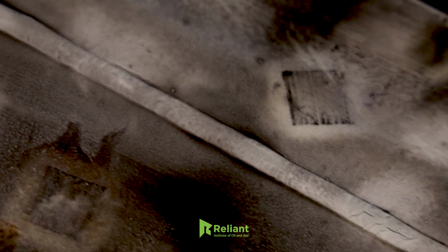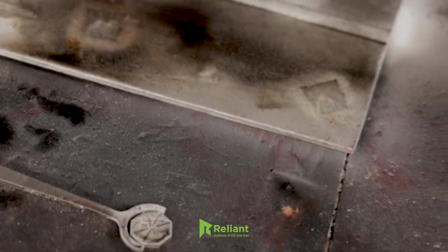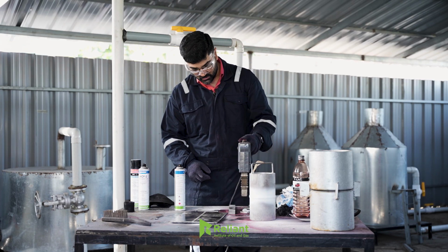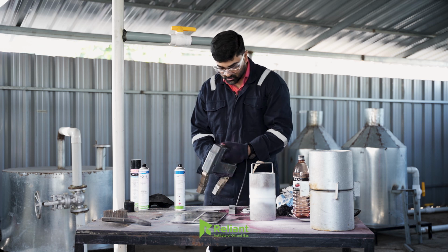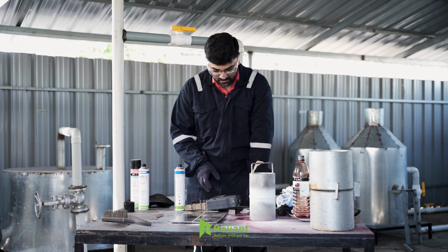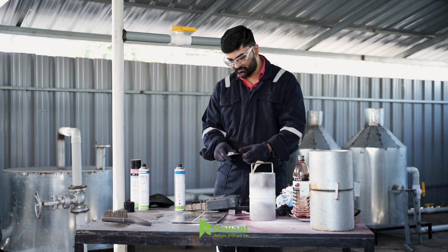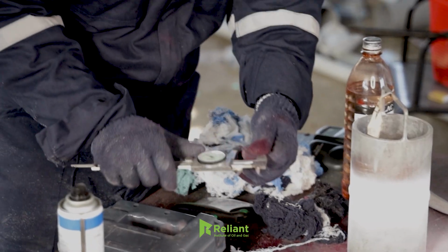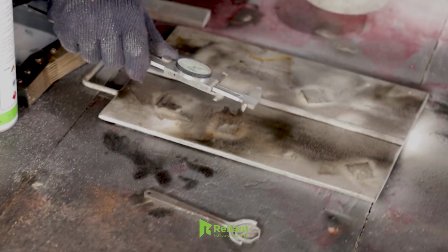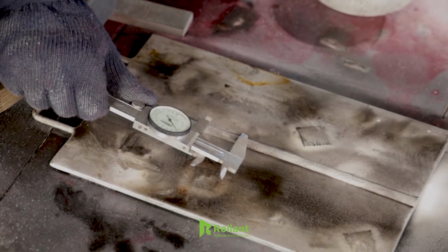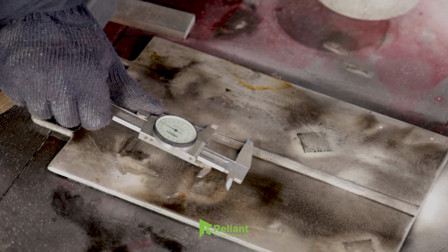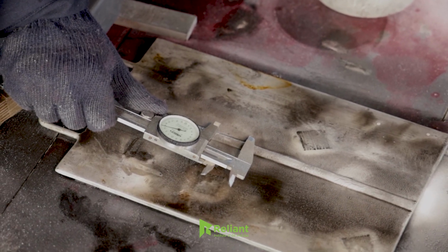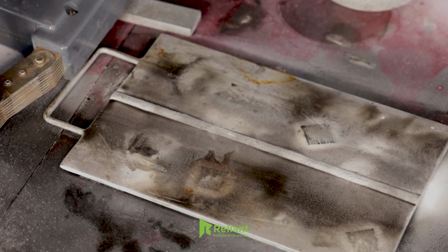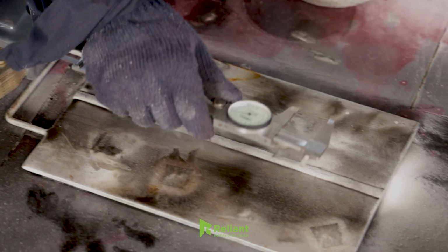Now the testing is over on the butt welded plate. Now I'm going to conduct the testing on the butt welded pipe. So before that, let us measure how much length the crack is. So the crack length is coming around approximately 28 mm, and this is approximately 26 mm.